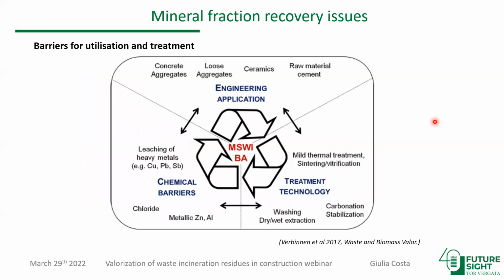So looking at possible barriers for recovery of the mineral fraction of bottom ash, we can recall the leaching of several elements ranging from metals to metalloids and salts, the presence of salts like chloride that can be a problem in bound applications, particularly for concrete, and different treatments can be applied depending on the intended application, ranging from washing to natural or accelerated stabilization, and use of even binders and additives.